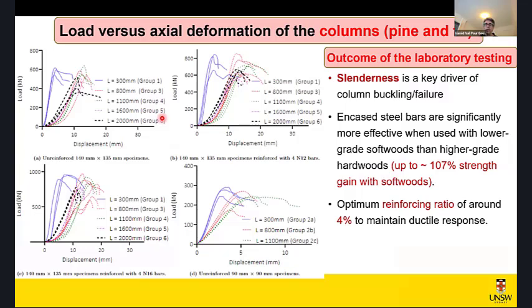So as I said, we tested a wide range of columns with different lengths. We even went down to 300 millimeter long, and we went up to 2.7 meter in height. And I have shown you some sample test results. Just two key findings in terms of the performance were: one, there is an optimum reinforcement ratio for the columns, and it's in the range of 3.5, and I would say it's closer to 4%. And substantial improvement in terms of the load carrying capacity, nearly doubled the load carrying capacity in the low grade softwoods when we use close to 3.5 to 4% reinforcement in those.